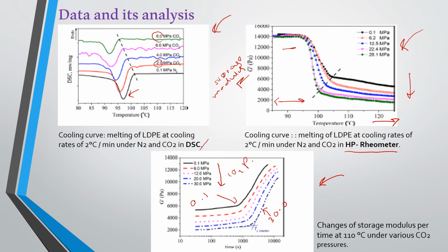In this case, their fixed temperature is 110 Celsius. So like I said before, the theory of the storage modulus strikes again, and that is the main theory they used to explain the behavior of polymer foaming. So when we look at the figure again, it shows how the storage modulus, which is G' right here, increased rapidly, and then reaches a relatively higher value at the end of the crystalline process. So after almost this point, it increases as the time goes up.